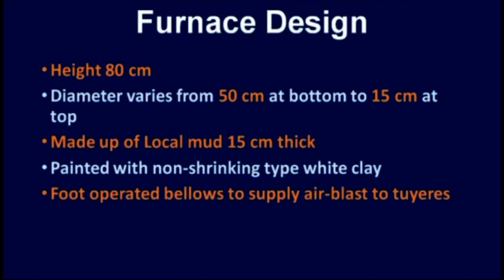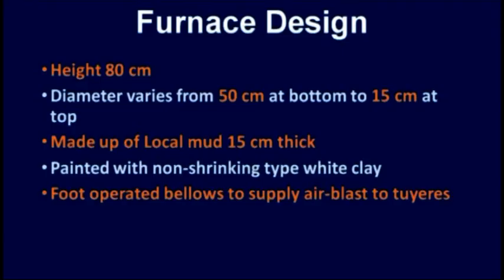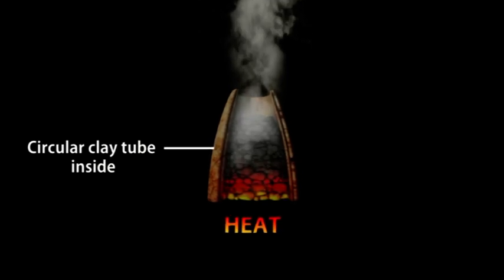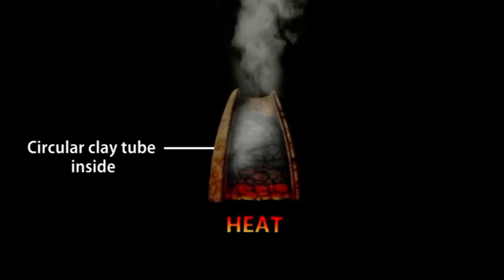Across the country there is variation in the height of the shaft furnace, but in Jharkhand, Bihar, Bastar, Madhya Pradesh, in these regions the height of the furnaces was smaller. The diameter at the bottom was found to be around 50 centimeter, and the diameter at the top of the furnace about 15 centimeter.